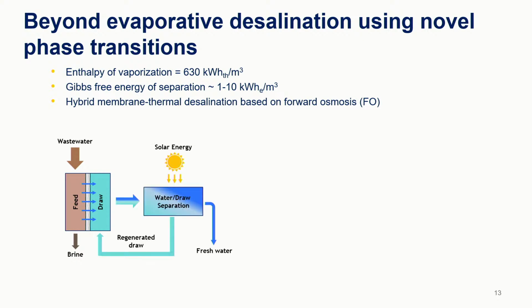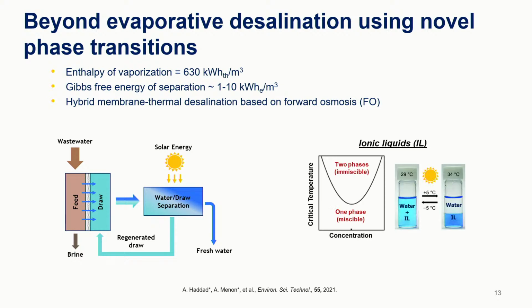So then we have a thermal separation step where the diluted draw is heated, but it does not have to be heated to temperatures close to boiling. We just have to heat to a critical temperature, which allows the water to separate from the draw, and then you can reuse the draw and you have your fresh water. And so the materials that enable us to do this are thermally responsive ionic liquids. Specifically, these are ionic liquids that exhibit a lower critical solution temperature behavior, or LCST.